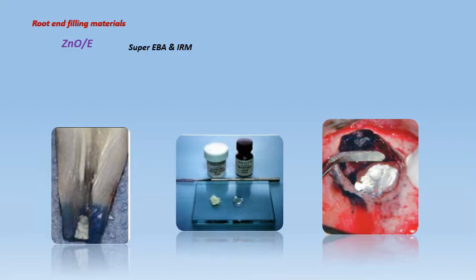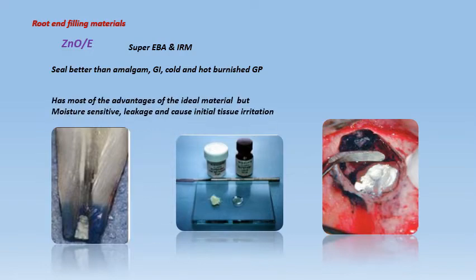The third material is zinc oxide eugenol. It comes as a powder and liquid to be mixed and applied in the retro cavity. Actually, it has a better seal than amalgam, glass ionomer, and hot burnished gutta-percha, but it is moisture sensitive, shows a little bit of leakage, and has an initial tissue irritation because of the eugenol content. Although it has most of the advantages of the ideal material, the moisture sensitivity is a killing factor regarding the root end filling materials.